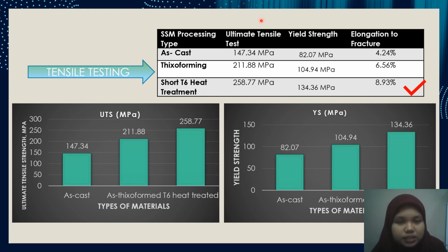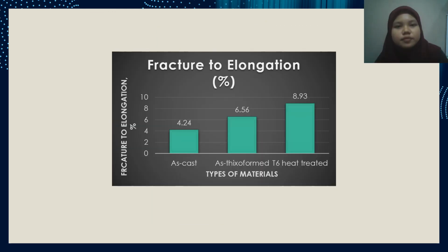However, the T6 heat treatment shows the highest results of all three for the UTS, YS, and elongation to fracture, as it attributes better ductility properties than the THIXOFORMED and the as-cast samples. Same as before, for the elongation to fracture, T6 heat treatment shows the highest value.